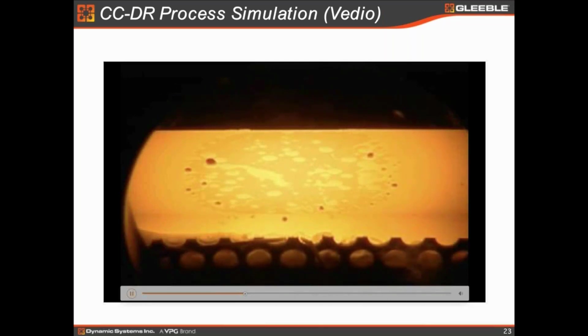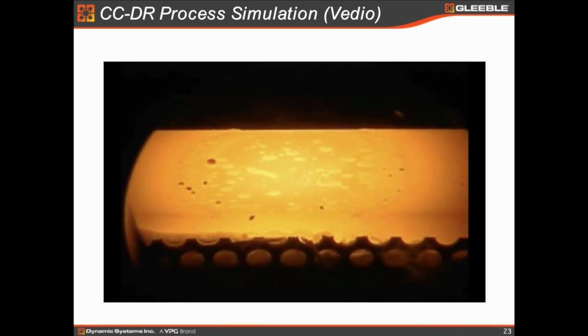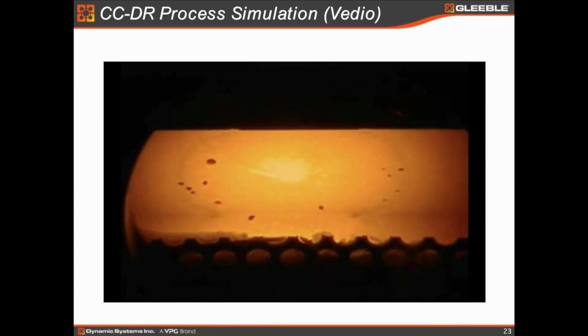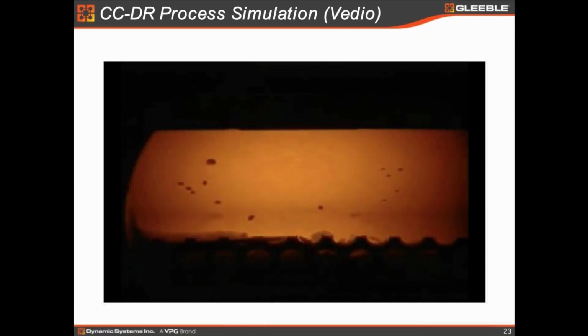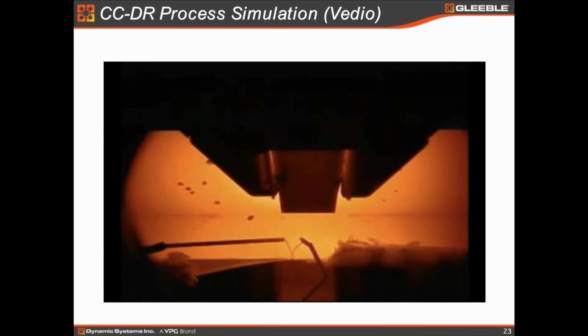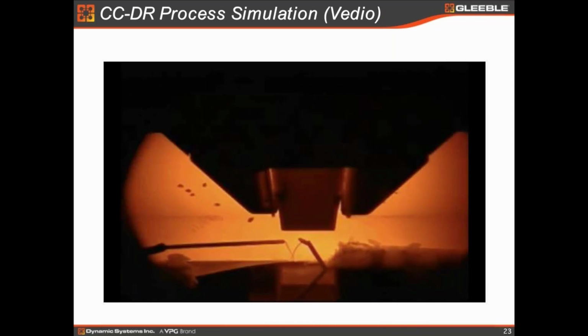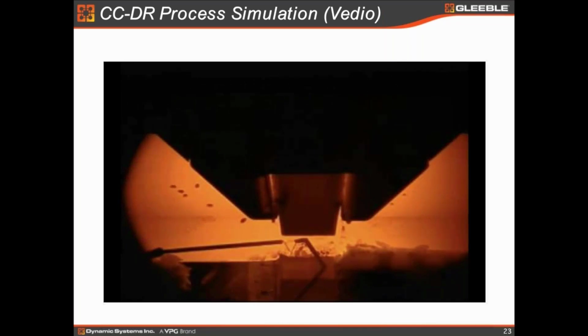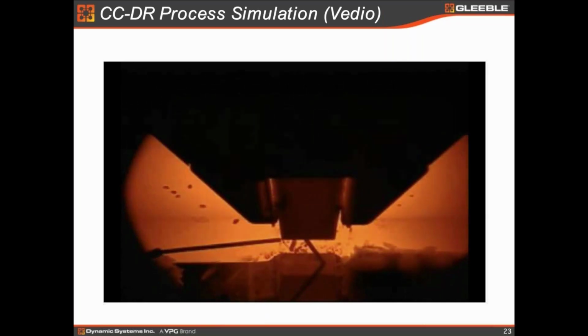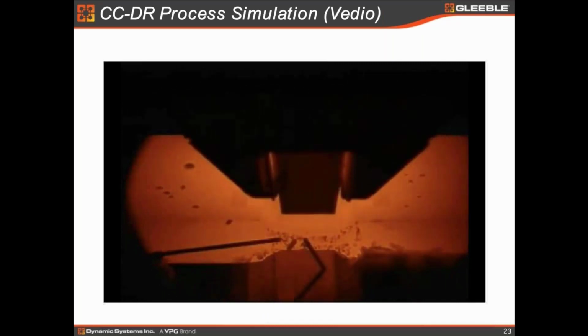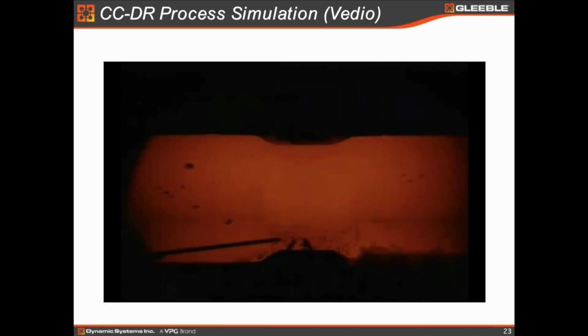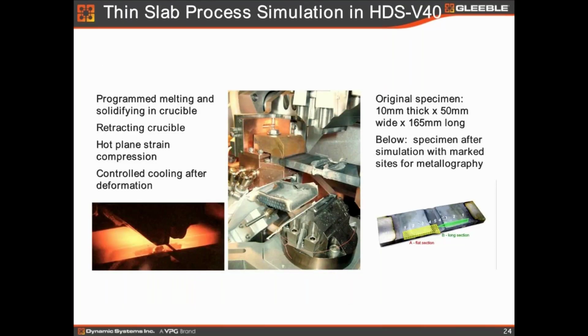You can do it without a crucible, because as long as it's not in a vacuum, the environment is fine, though normally inert gas would be better. So it's kind of fully melted, because you can see it bubbling in the center. Then you control the solidification, and you can do the direct rolling right afterwards, as you can see here, because it's all in situ simulation of the CCDR process. You can do as many hits as you want: 1, 2, 3, 4, 5, whatever you want. It's not a problem. We can control the temperature, the strain, the strain rate, and the interpass time, as you see in your real process flow.